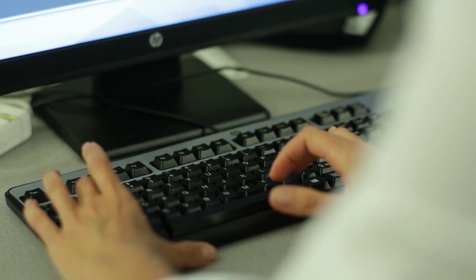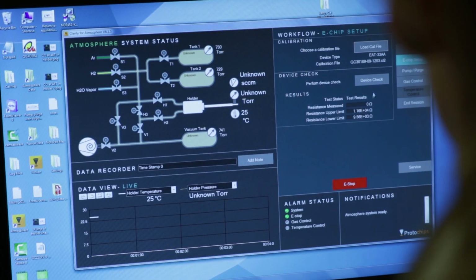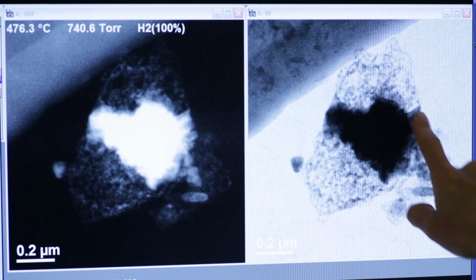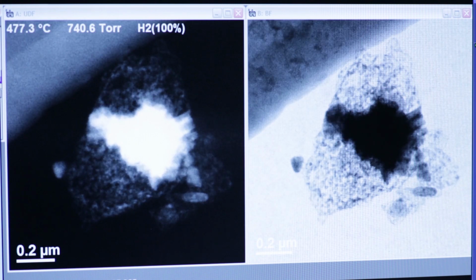With the capability of studying the reaction of the catalyst at different magnifications, we can not only observe the types and the location of the coke formation, but also we can study the reactivity. For example, in molybdenum carbides, we found that the surface coke was very reactive and was removed somewhere between 200 degrees C and 370 degrees C. This is very important because coke deactivates the catalyst and decreases the life of the material. What is really important about this in-situ STEM microscopy is that molybdenum carbide can be regenerable, and also that this type of reaction can be missed by other techniques since it is performed at such a small scale level.